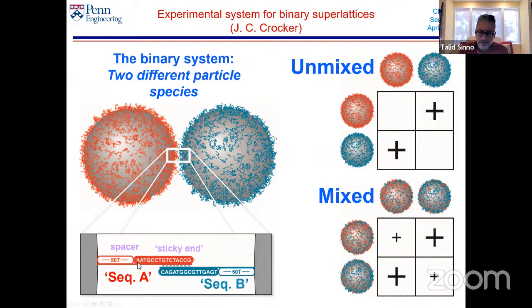In this case, the red strands are only complementary to the blue strands. So red and blue bind together, red and red don't, blue and blue don't. But what we can do is mix a little bit of red strands with the blue strands, and have systems where a mostly blue particle will interact with another mostly blue particle through the red-blue interactions. But this is a weaker interaction. We can tune it by changing the mixture of red and blue. If I have equal amounts of red and blue on every particle, then I effectively have a single component system. So we can go all the way from a single component system to a purely AB system by changing the ratio of the red and blue strands on the particles. That's the universe of interactions we're going to look at today.